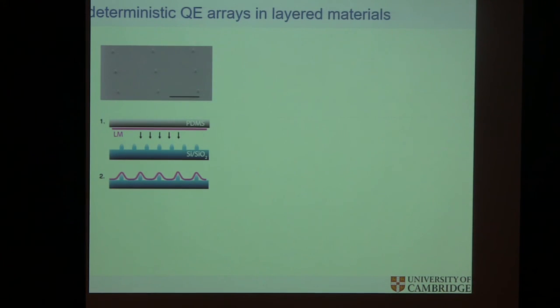So we said, could it be because of local perturbations that lead to perhaps strain, that lead to these confined excitons? And there were a couple of papers that indicated this might be the case. So we said, okay, let's make structures with Marcus's group here. And Paul is somewhere here. Such that we have these tiny needles, and then we can put these layered materials right on top. So instead of a nice clean substrate, let's have these needles, and then put the layers. And then let's see if we can induce exciton confinement in these materials.